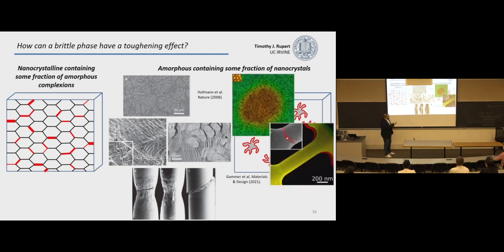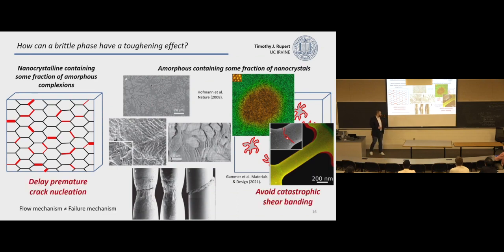You can even see examples of this in the metallic glass one from really beautiful in situ experiments that people have done recently. Here they have a deposited amorphous material with little tiny nanocrystals inside the material. And what these people were doing is pulling on this and showing that the shear band deflects around that particle.